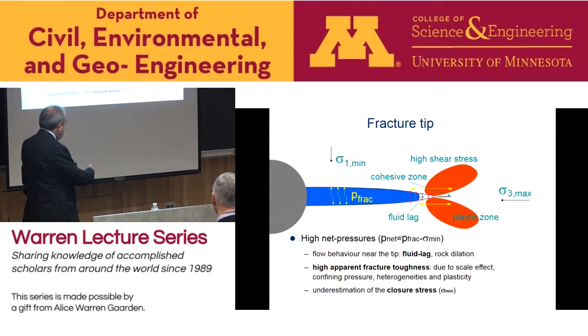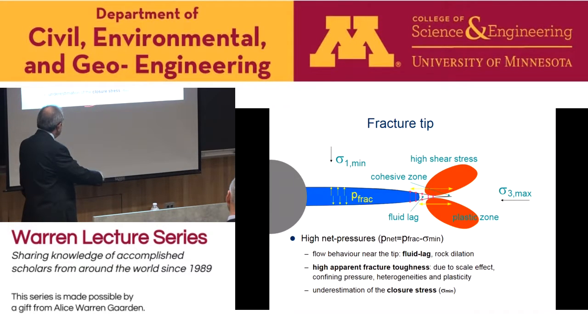Also later I will show that when we do a calibration test in the field and measure pressure versus time, and then invert the pressure versus time to determine some formation parameters like permeability or the closure stress, it's very likely that using elastic models we underestimate the closure stress. And if we underestimate the closure stress, the minimum stress, then we will need higher pressure in the field to propagate the fractures.